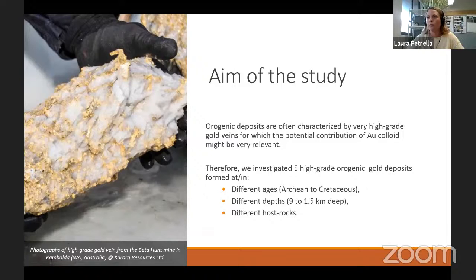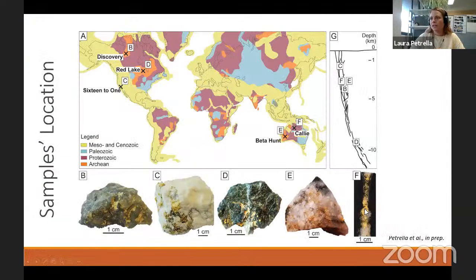So what we did is select samples from 5 high-grade orogenic deposits that were formed at different ages, different depths, and in different host rock. And we looked at them using transmission electron microscopy and tried to find evidence for colloidal gold. So these are the 5 samples that we used.